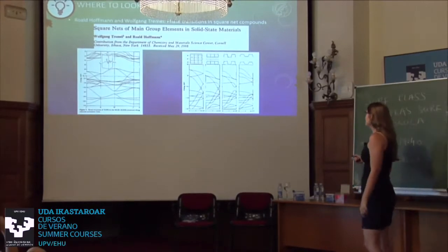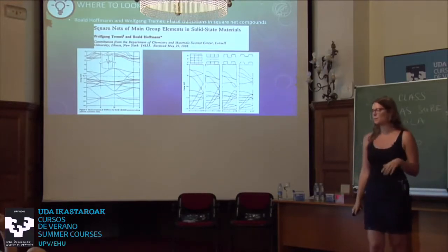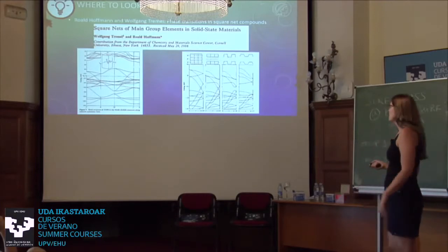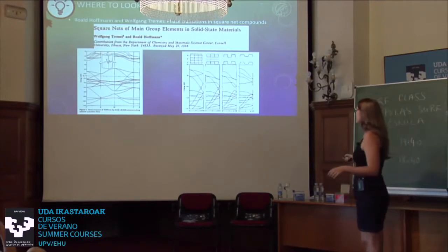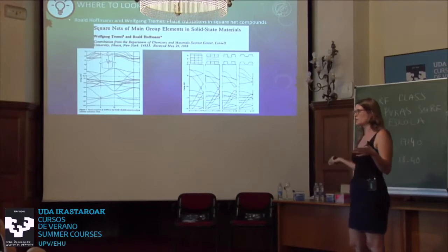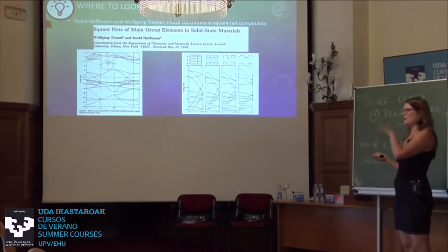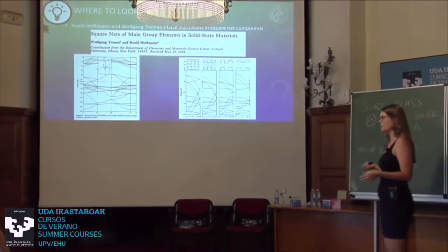And so what he writes in this paper is, okay, when you have a compound where atoms are arranged in a square net, you have those crossings here, and this was before people cared about Dirac electrons or anything. He just noticed that they often distort and gap out because there's some residual density of states at the Fermi level, so they don't like it. By the way, this is not necessarily a half-filled band in a non-symmorphic system, which is just a Dirac crossing. So it's not forbidden to be there, but it's just still energetically not favorable.